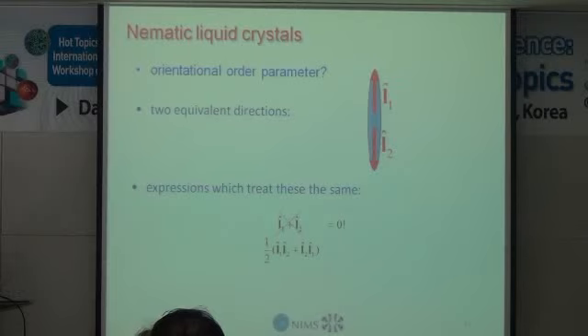Or we can form the outer product. We could make a dyad of these guys. Now this is much better. It turns out that L2 is just minus L1, so these two things are the same. And so this quantity, this second-rank tensor, is in some sense the right order parameter because it remains invariant if you rotate this thing n for n, and yet it describes the orientation perfectly well.